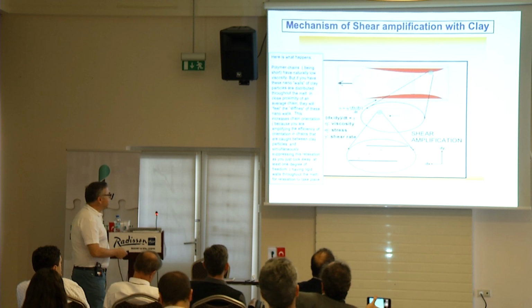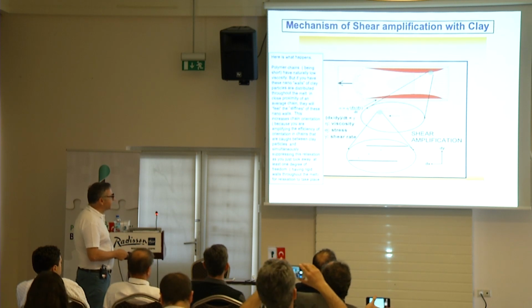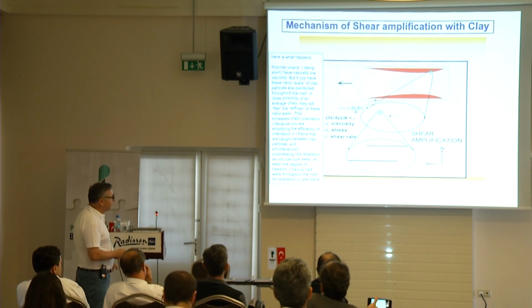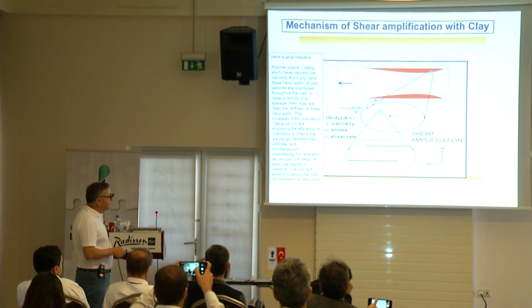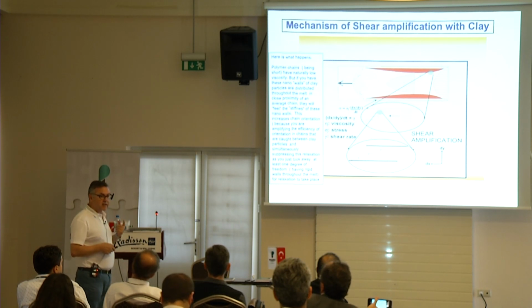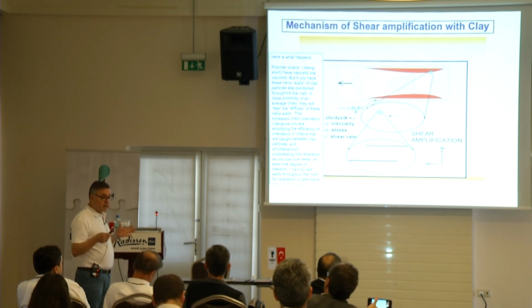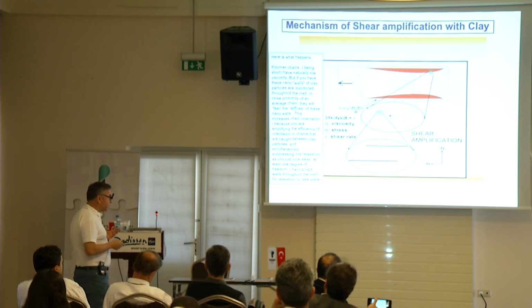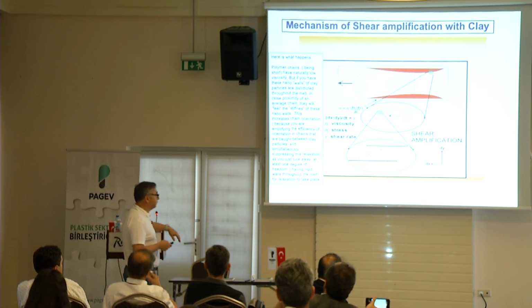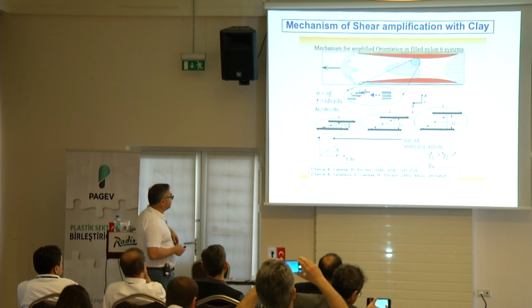I'm almost there. So it's a shear amplification. What happens in this process is that the materials in between are so close to each other that you amplify the shearing, and then two things happen. When the polymer chains are close to the solid surface, their mobility goes down. Because their mobility goes down, plus you have shearing, they dramatically orient. Because the mobility goes down, they don't disorient. That's the key, even though the nylons have short chains. Polycondensates are all short chains, 40,000 molecular weight, no more. So the dramatic shear amplification occurs in the shearing action.